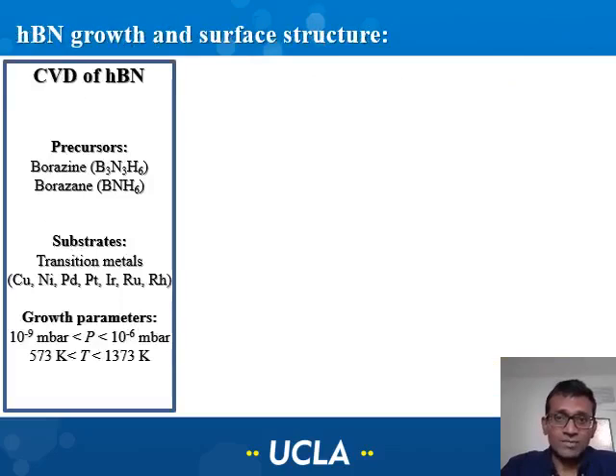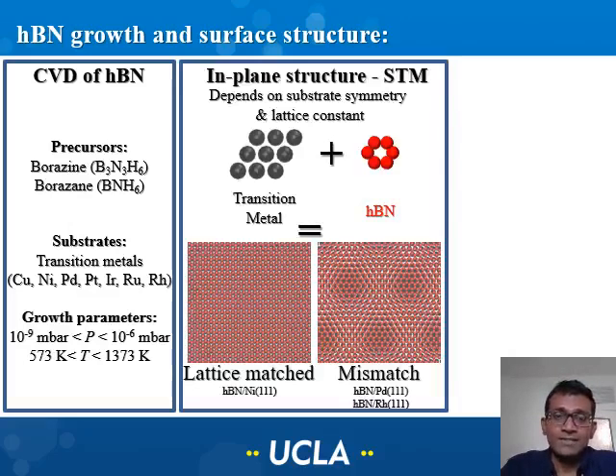Among these materials, hexagonal boron nitride is commonly grown via chemical vapor deposition using one of the two precursors, ammonia borane, which is a solid, or borazine, which is a volatile liquid. And the most commonly used substrates are transition metals, which catalyze the decomposition of these precursors. And scanning tunneling microscopy studies over the past decade conducted on these two-dimensional layered crystals, and in particular on hexagonal boron nitride, have shown that the layer quality depends on the type of substrate used.